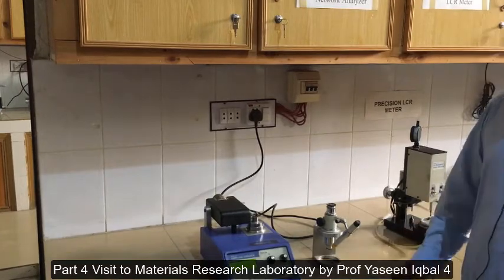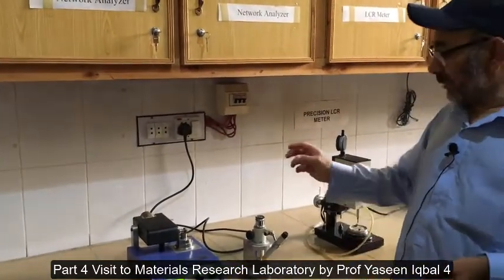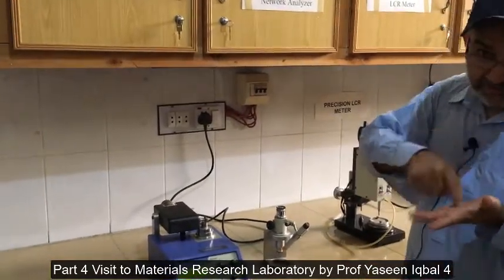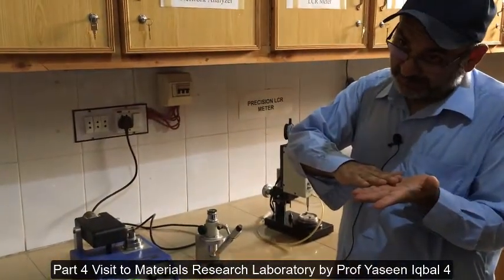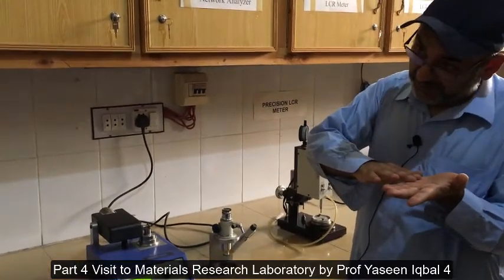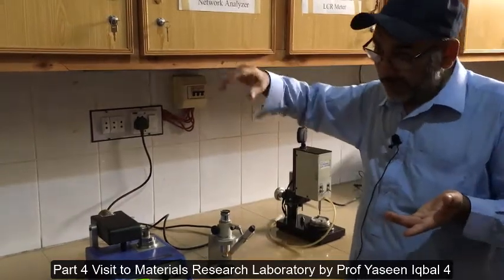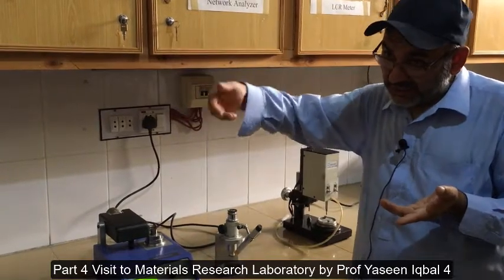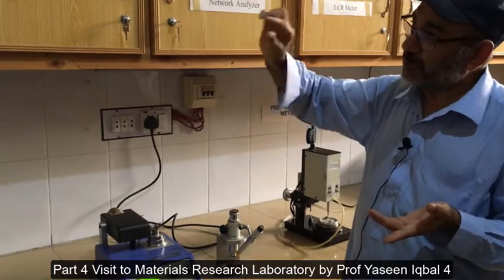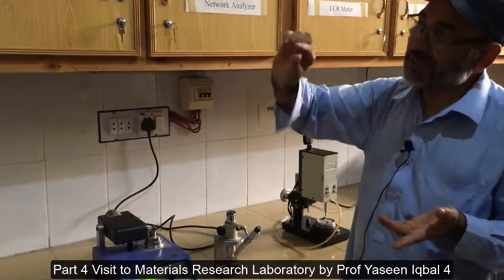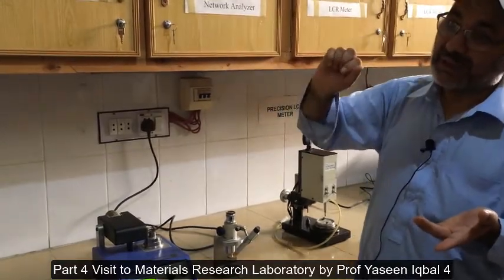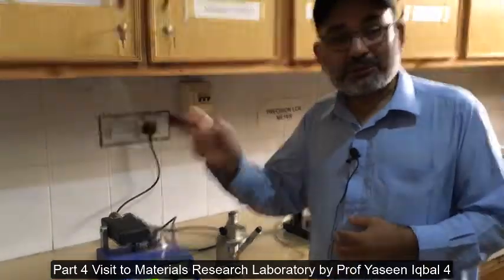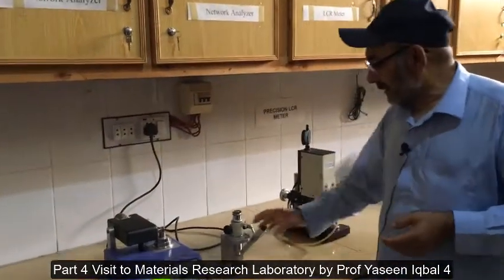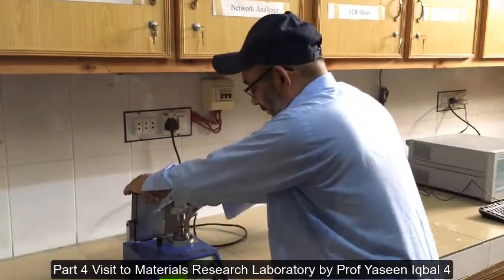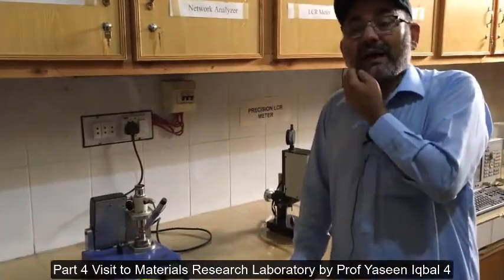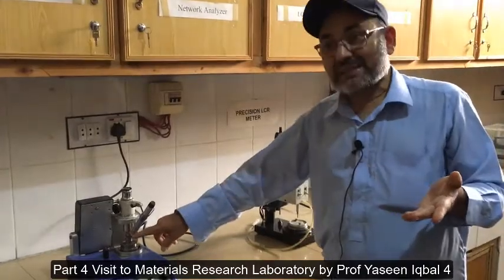So how do you know it is 25 micron thick? We have a calibrated optical microscope. You focus the bottom of the dimple and focus the top of the dimple, the top of the sample from where you started. And that difference, when you have a micrometer in the optical microscope, tells you how much difference there was between the two foci, right? That difference tells you about the thickness of that dimple. So once you have done that, then you take it to the argon ion thinning. What is argon ion thinning? You can check this. This is a small microscope type thing in which you can check the thickness time and again.